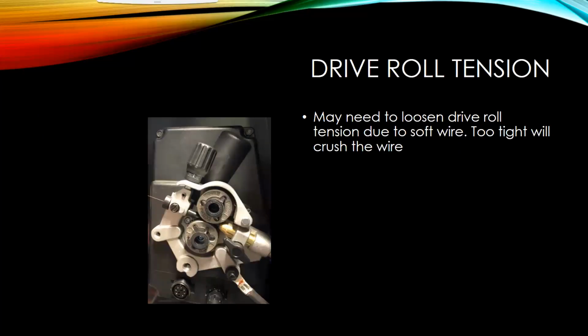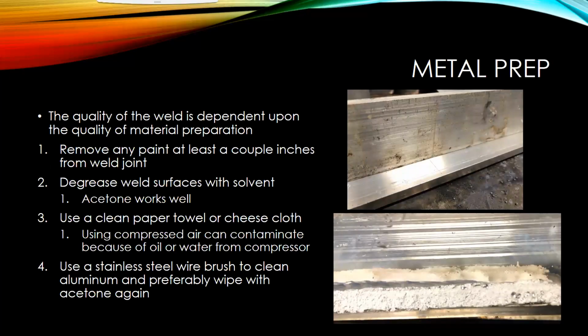Oh, that's a really good question. That's one of the big problems. With aluminum, you're really trying to get that oxide layer off of that outer shell. That's where material prep really comes into play and really helps out. One of the things that will really help with getting that oxidation off is using a stainless steel wire brush. When you use that, it'll help break that oxide layer, and it's going to help you get a smoother weld and adequate penetration. Okay.